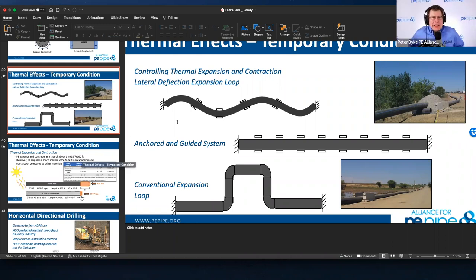The fascinating thing about what you just said is most people in the audience, Richard, don't believe you. But PVC does fail with fatigue. It's already a brittle product at temperature, but once you start adding cycles to it, it will fail. That's why some of the failures are so spectacular, because it splits and runs. But ductile doesn't fail that way. It doesn't fail because of fatigue. It is indeed the strongest material. It fails because of the presence of oxygen. So its failures are not spectacular, but they occur more frequently. It's a crazy, crazy dichotomy that we see in the various materials.